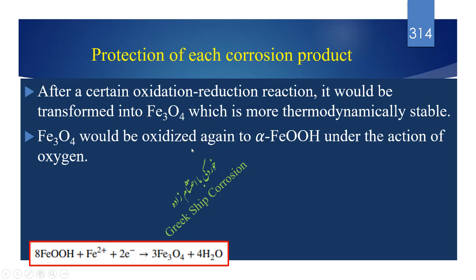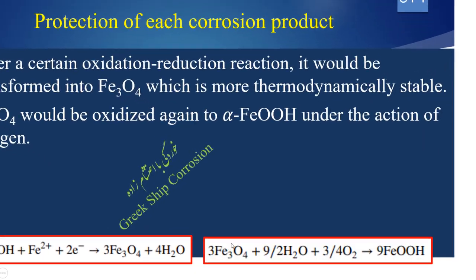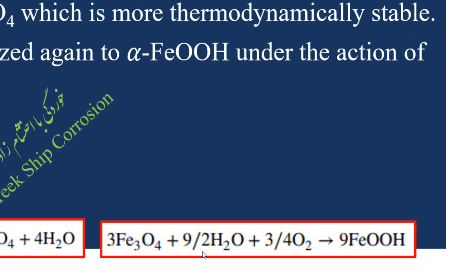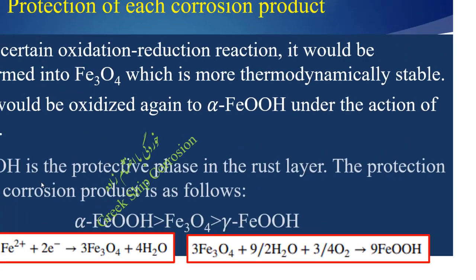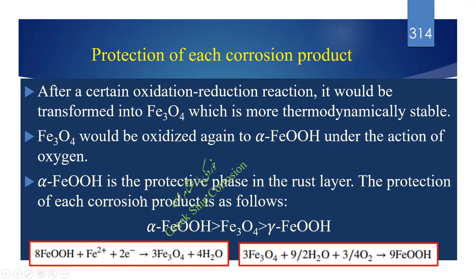Fe3O4 would be oxidized again to alpha FeOOH under the action of oxygen. 3Fe3O4 + 9/2 H2O + 3/4 O2 yields 9FeOOH. Alpha FeOOH is the protective phase in the rust layer. The protection of each corrosion product is as follows. Alpha FeOOH is more protective than Fe3O4, and Fe3O4 is more protective than gamma FeOOH.